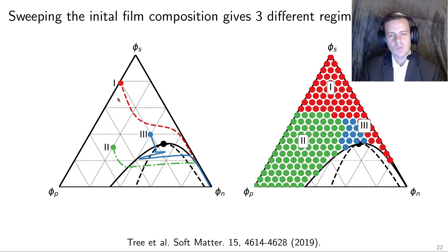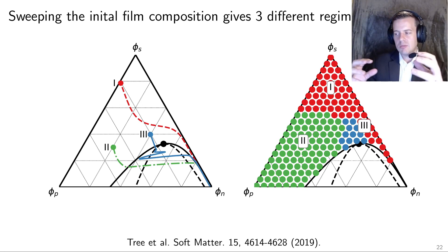Time and distance film thickness can be collapsed to a single variable, which is what we know for these kind of semi-infinite problems or when time is less than the diffusion time. We can play a game where we vary the initial film composition. Then we can see at this early time what all of the different behaviors are. We observed broadly three different regimes of behavior. One is this red, where nothing happens, where I get no phase separation initially. In two, I get a phase separation, but it just sits there as two immiscible domains. The most interesting case is three, where I get immediate spinodal decomposition. Even though I'm outside of the spinodal window, if I pick something that's close enough, it will immediately begin to phase separate.